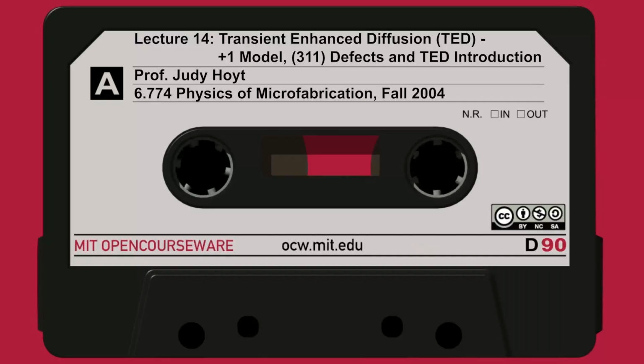And particularly for boron, which is a light ion, because of the nature of the type of damage it does, this intermediate dose range is a real problem. And this complicated behavior can occur over a wide range of boron doses that are used in practice in CMOS fabrication. It's because the nature of the damage created by boron is different. It's a light ion, so it's not doing very effective nuclear damage, at least until you get towards its end of range. So you'll hear people say, oh, boron's a lot harder to activate than arsenic. Indeed, it is. It's harder to repair the damage from a boron implant in silicon than from an arsenic implant in silicon.